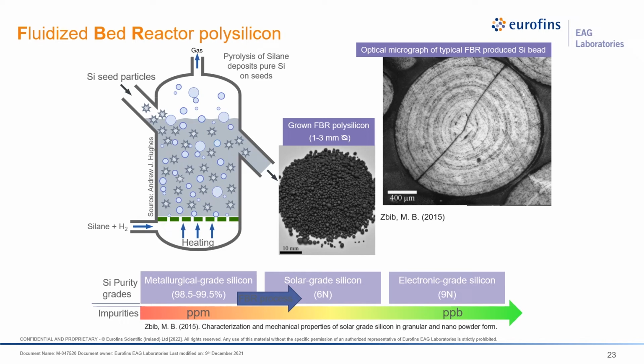An FBR process, a relatively recently developed refining process, is used to grow solar grade silicon as shown in this schematic, where silicon vapor is created in the reactor by using silane and hydrogen that deposits on the seed particles that have been fed from the top. After a certain threshold value, you will grow 1 to 3 mm polysilicon grains. When you look at the microstructure of the bead grown in the FBR reactor, it looks like this. It shows a tree ring structure suggesting layered growth of silicon in a hydrogen-rich environment.